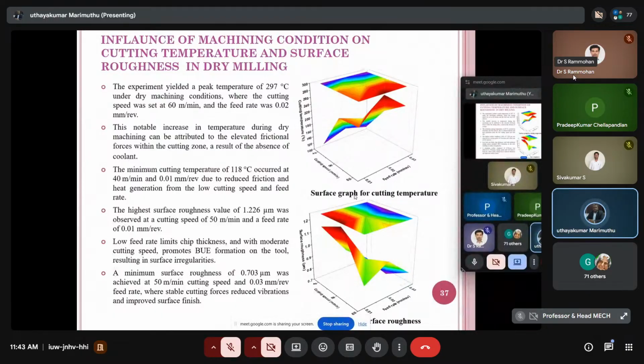The experiment yielded a peak temperature of 297 degrees centigrade under dry machining conditions, because there is no coolant used, where the cutting speed was 60 meters per minute and the feed rate was 0.02 mm per revolution. This notable increase in temperature during dry machining can be attributed to the elevated frictional forces within the cutting zone, a result of the absence of coolant. Yes, that is important. The minimum cutting temperature, 118 degrees centigrade, occurred at 40 meters per minute and 0.01 mm per revolution due to reduced friction and heat generation from the low cutting speed and feed rate.